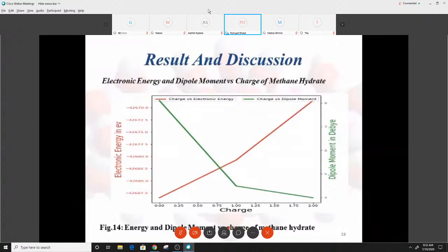This slide of result and discussion is used to compare the electronic energy and dipole moment of methane hydrate. This graph shows that the electronic energy is increasing with increasing charge, which is shown in red line, while the dipole moment is decreasing with increasing charge, which is shown in green line. Similarly to the previous slide, here we also compare the electronic energy and dipole moment of cavity. Here we also found a similar type of graph where the electronic energy is increasing with increasing charge, while dipole moment is decreasing with increasing charge.